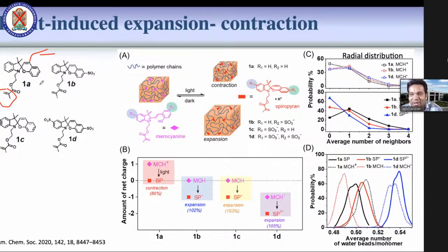Gel can be prepared as an organogel as well as a hydrogel. If you use a water medium and swell in water, you can create a hydrogel. If you use organic solvents, you can create an organogel. So here, this acts as a monomer, and you can create different substitutions on the backbone of this spiropyran structure depending on the requirement. When we create the gel structure, this is a gel cross-linked with the spiropyran.